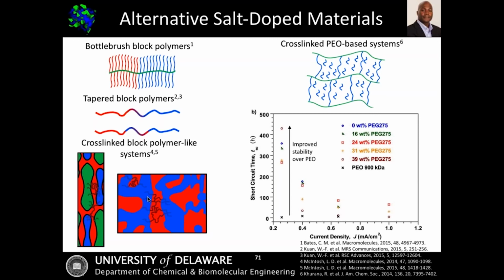However, one of the things they were able to find in these types of systems is that they actually had improved short circuit times, meaning that they were able to resist some dendrite formation even without having that high modulus material. So one of the things I just want to point out there, even though there are some well-established rules in terms of having a high modulus system, we may find as we do more work in the nanostructured systems that that's not exactly a hard and fast rule.